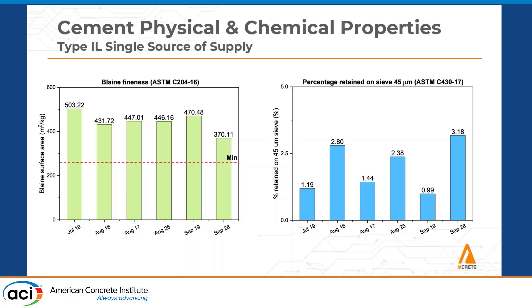The problem, which has been reiterated throughout this presentation, is that unfortunately the change was not communicated. So this went to the producer, went into their silos, and went into multiple slabs and elevated decks. We were having some issues and then it turned into shrinkage and some pop-outs and things of that nature.